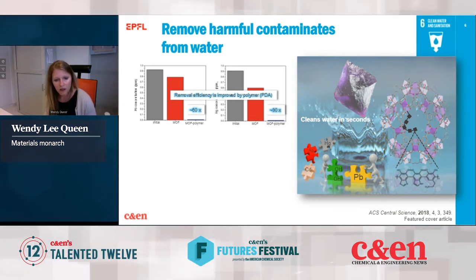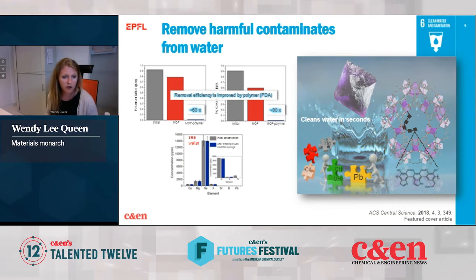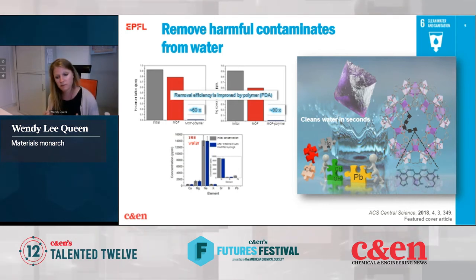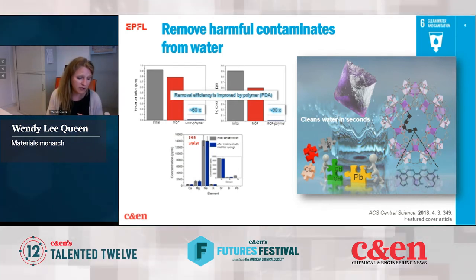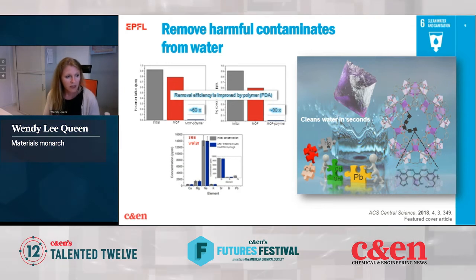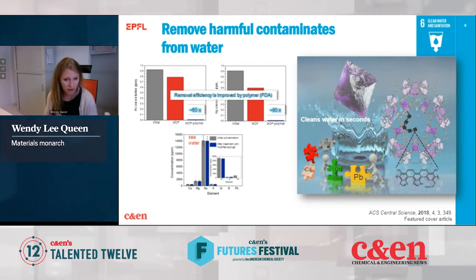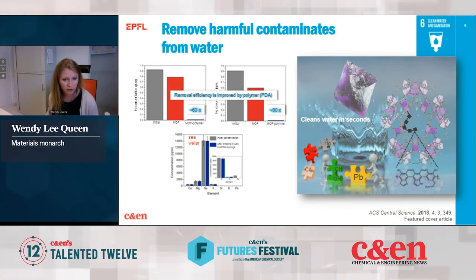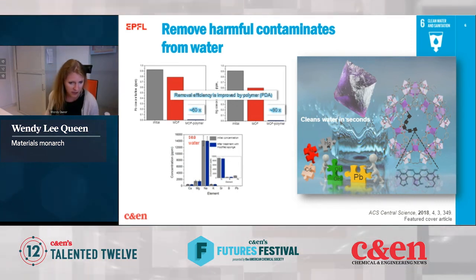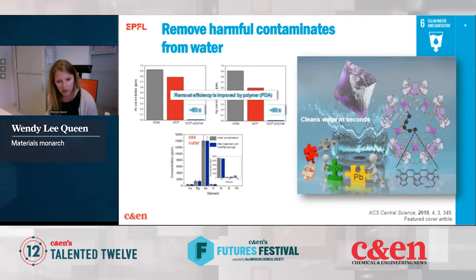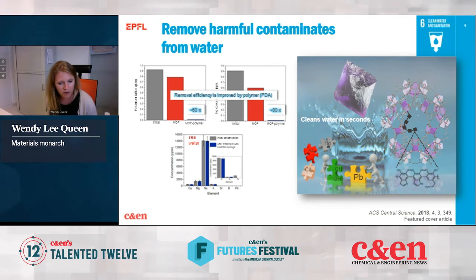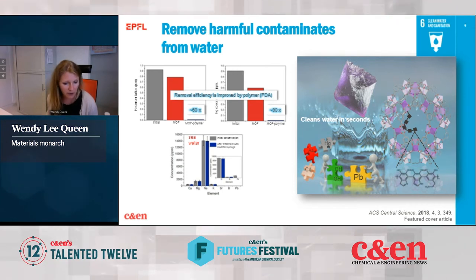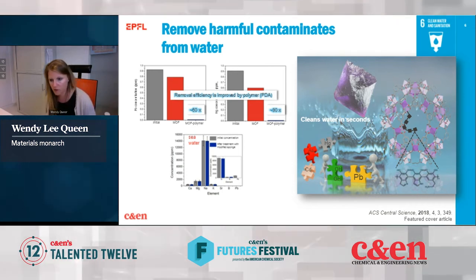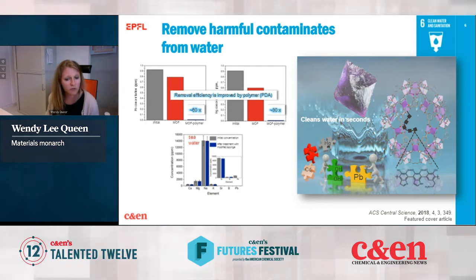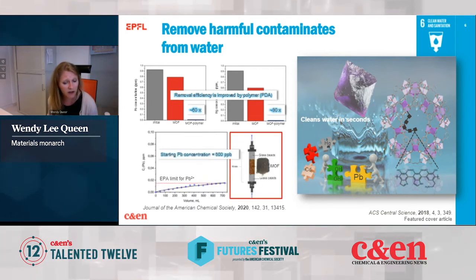these metals. Interestingly enough, the materials are also extremely selective. So what this means is that if we put our materials in a very complex matrix, it doesn't decrease its efficiency. So here I'm showing you an extremely complex matrix, that's seawater. What you'll note is that the concentration of sodium is 14,000 times that of the lead that we've spiked in. What we find is that the material will selectively remove the lead and leave behind these other metals in the solution, which is great. Because of the material's performance, we've begun incorporating them into filter devices.